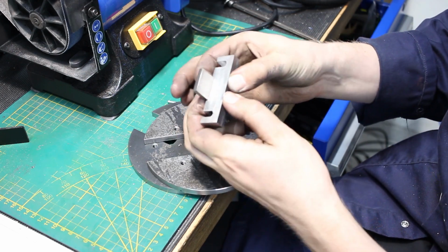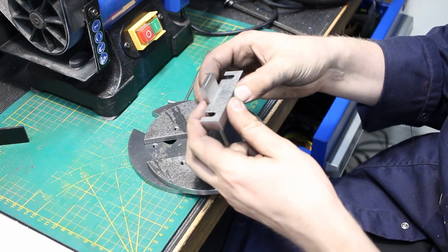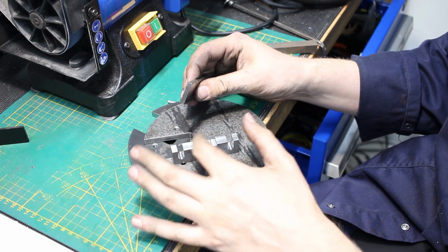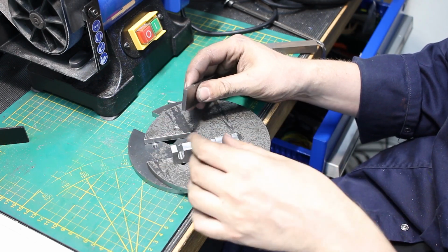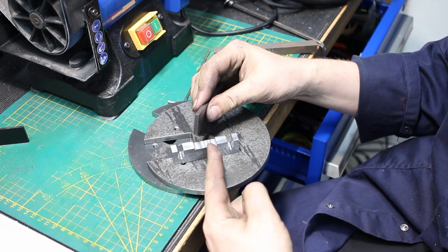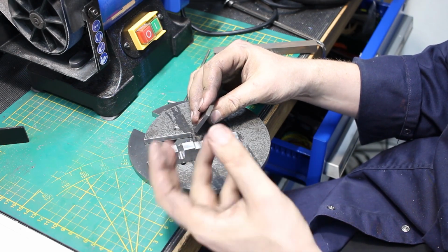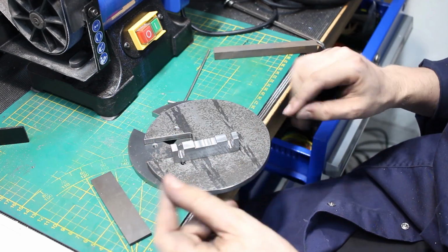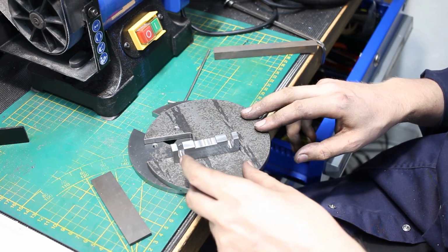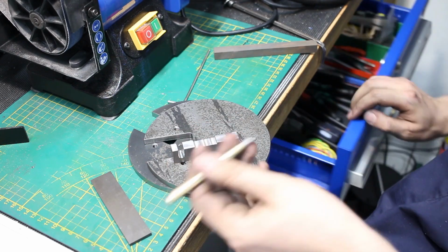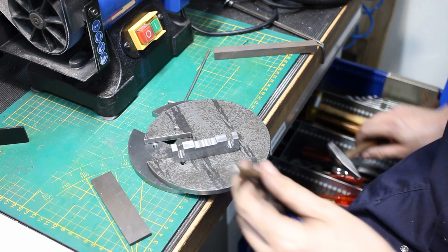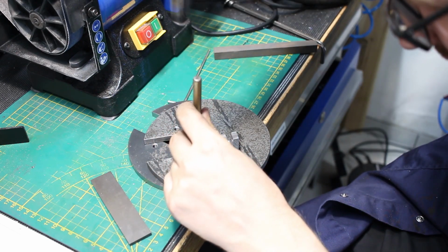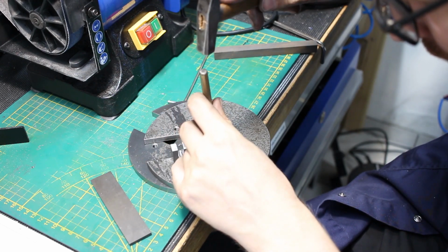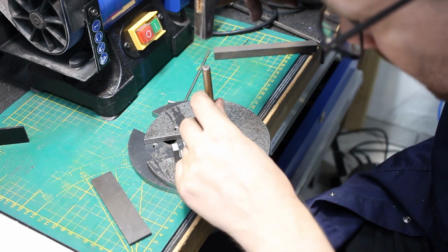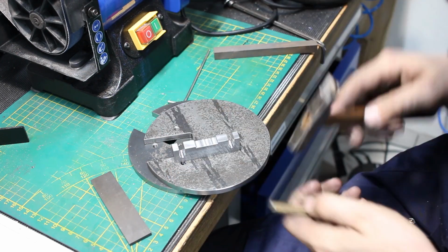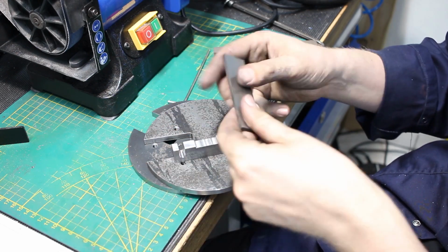Next step will be to take these high-speed steel blanks, orient them correctly like this, and silver solder them in. For silver soldering, I want to clamp them together with vice grips. But the problem is when you clamp a silver brazing joint completely tight, there is no way you get your silver solder over the whole surface between the gap, and that's what gives you the strength. So the way I learned to do it during apprenticeship, we took a big old center punch, and we put 4 dimples in each corner of the surface you're brazing or soldering.